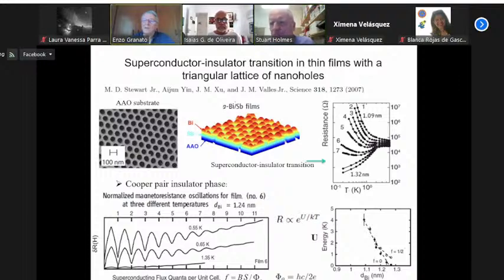I see. But then the hopping conductivity is not thermal activity. It does have a temperature dependence. No, but it's not thermal activity. It doesn't have an exponential behavior. For variable range hopping? Yeah, it doesn't have an activation exponential of something. Because here, you see in the figure, the resistivity which they find is proportional to the exponential of U divided by kT. So U is the activation energy for this system. And so this is the quantity which I can infer from the calculation.